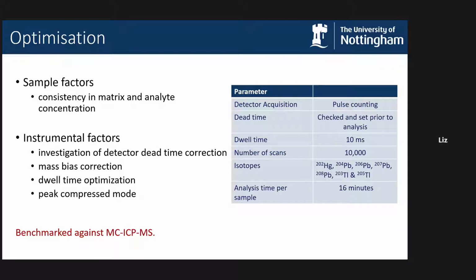So where the detector is getting counts, there's a little bit of dead time where when it's recording one count, it can't measure another count if it arrives at the detector very shortly after. So there's a correction there for that. And we were maximising, as I said, the lead-204 signal whilst keeping the lead-208 below the detector trip point. So that's how we optimised the sample factors, but then we optimised a number of instrumental factors as well. So that detector dead time correction, we investigated with a series of standards for each of the isotope pairs, and we optimised the isotope intensity ratios against the intensity signal of lead-208.